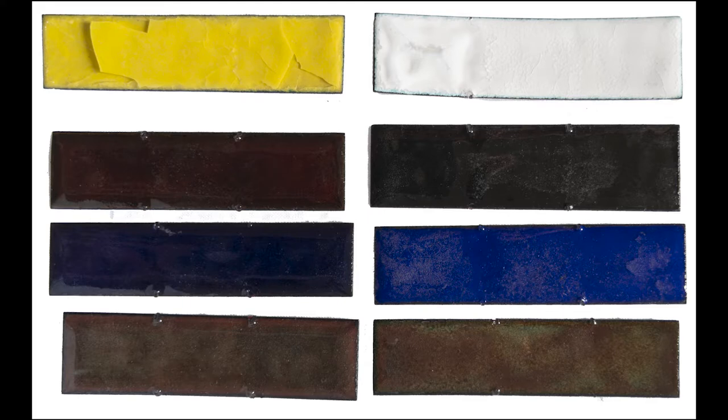Now let's get on to the experiments. For my first set of test strips, I wanted to get a better grasp of the variable hardness of each color of enamel to be used. I did this in two ways. The first was to observe through the kiln window as it was being fired and notate exactly when it hit its softening point — switching from a crystalline or sugar-looking surface to that smooth enamel look.